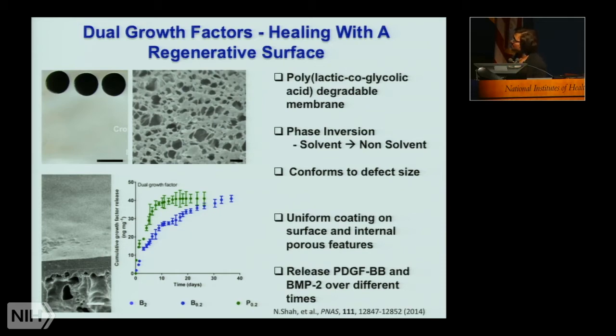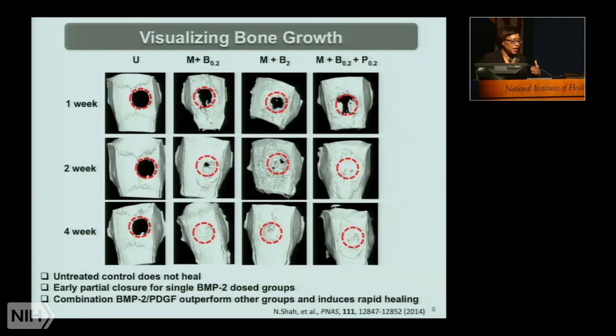When we look at the in vitro release of this simple system, we see that there's a slight delay of one over the other. So PDGF comes out over a period of the first week or so, whereas the BMP2 is being released over a much more extended period, which goes out to about 30 to 32 days. Then we looked at what happens when we have single versus dual growth factors, and we also looked at dose.